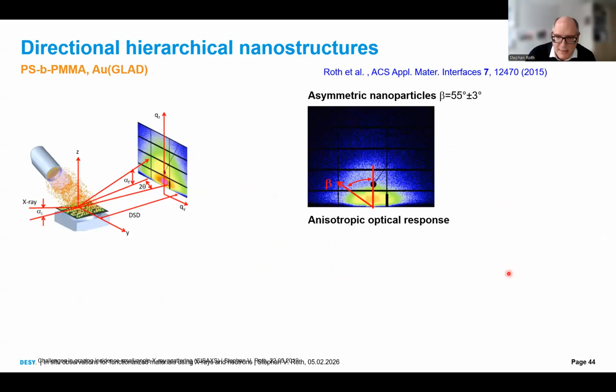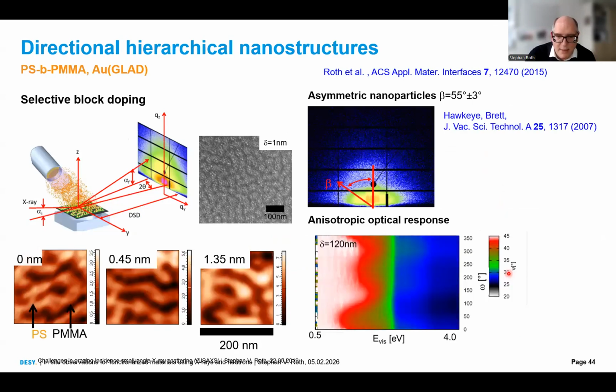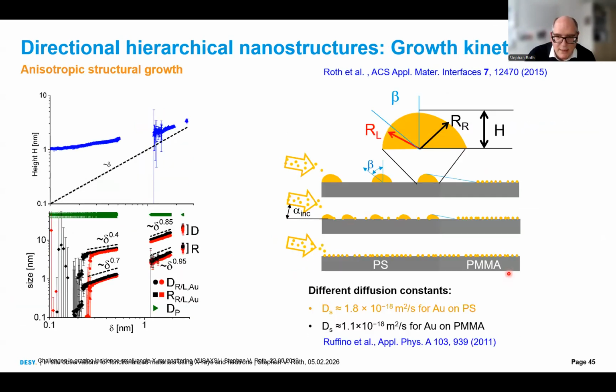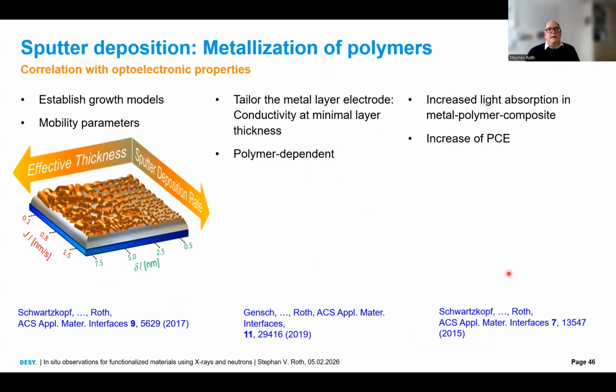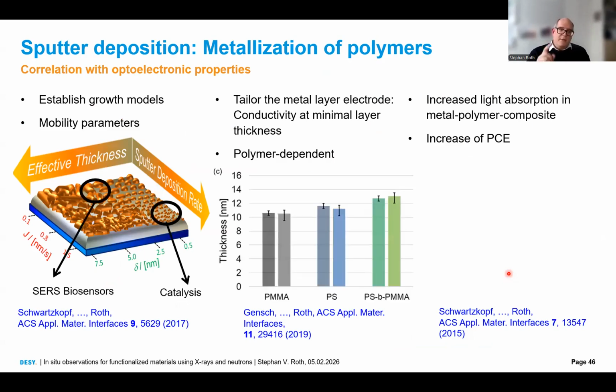And the nice thing is, maybe I go through this a little bit faster, is this here. We can give you for all sputter rates, for all thickness, a nanostructure, and we can compare our percolation threshold from GISAXS with what we measure. And this is what you see, light to gray. This is GISAXS, this is measured.